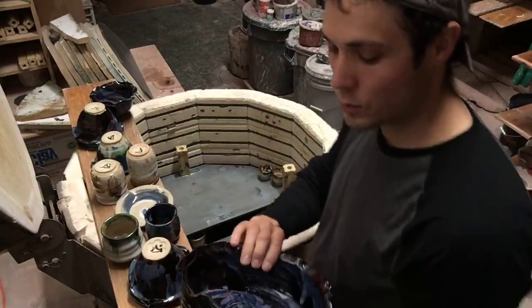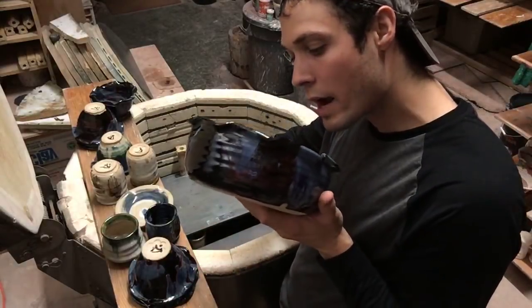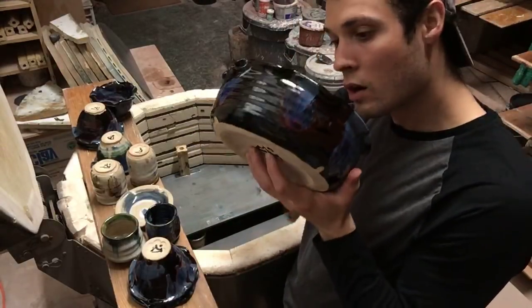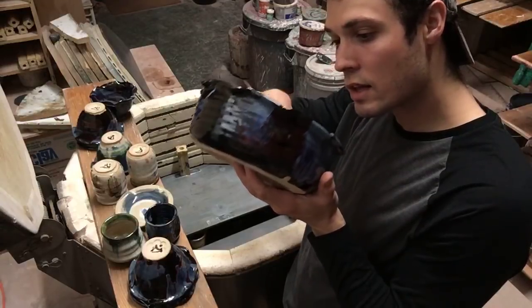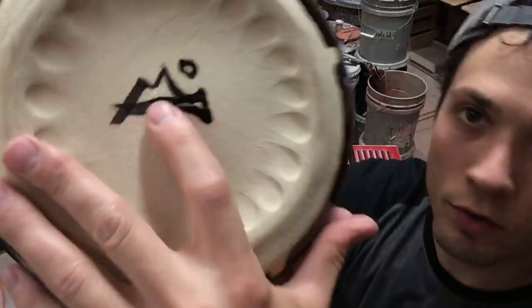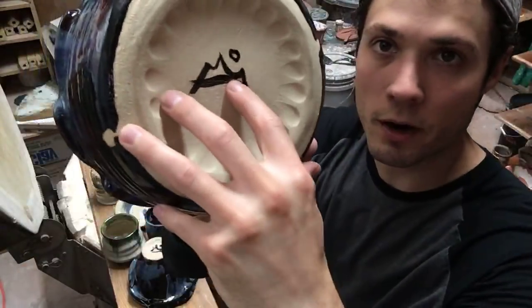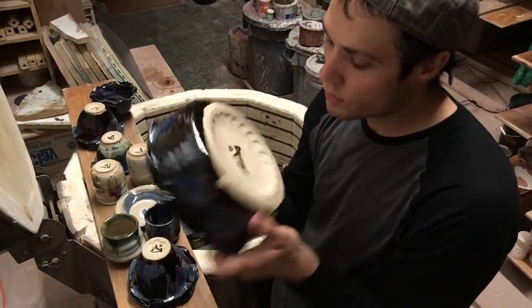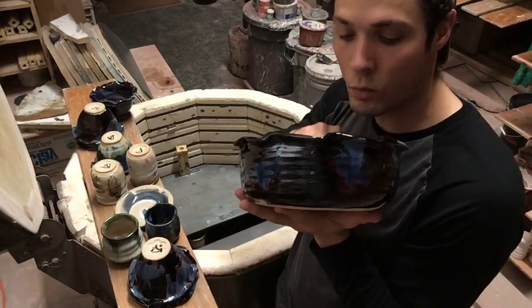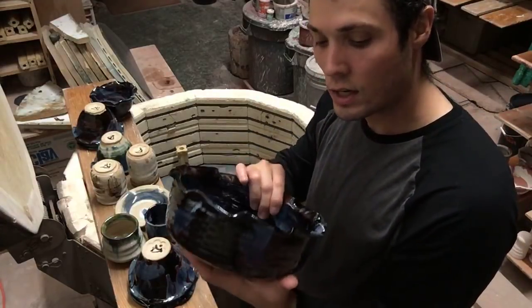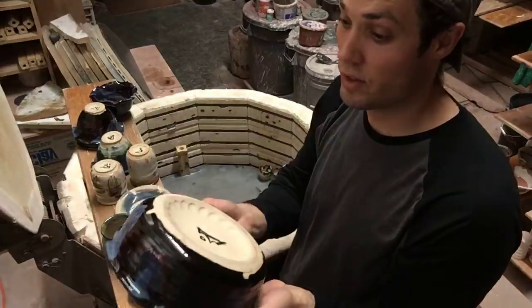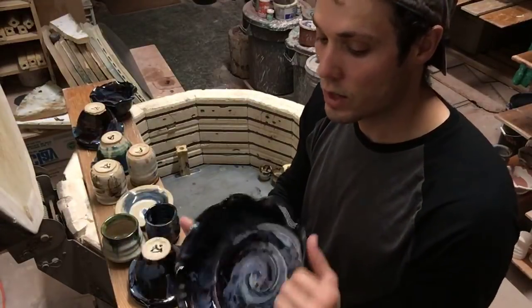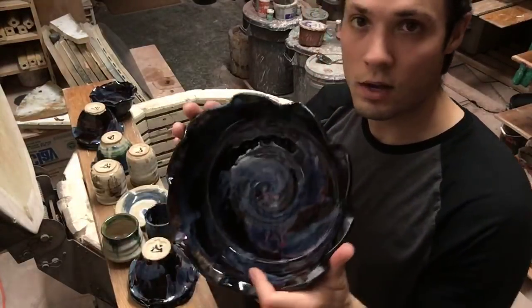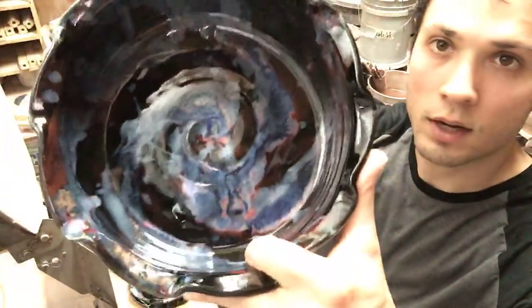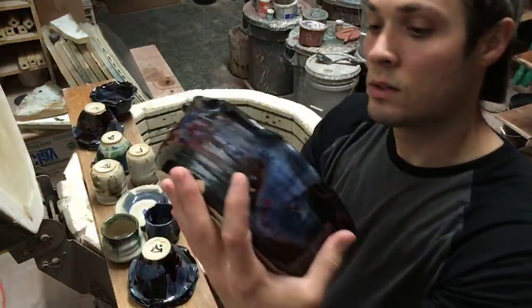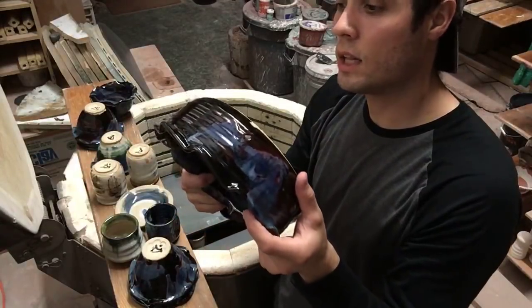So this pot was cracked before I fired it. Oh, that's alright, I might have to test that. Huge crack, so I painted over the crack, but cracks get bigger in every firing. But it didn't go all the way through. I might still test it with water to make sure the glaze covered it. But it looks like everything else about it turned out perfectly. So I'll still sell this one, but it'll be discounted because everything else turned out great. But yeah, it's got a crack in the clay.